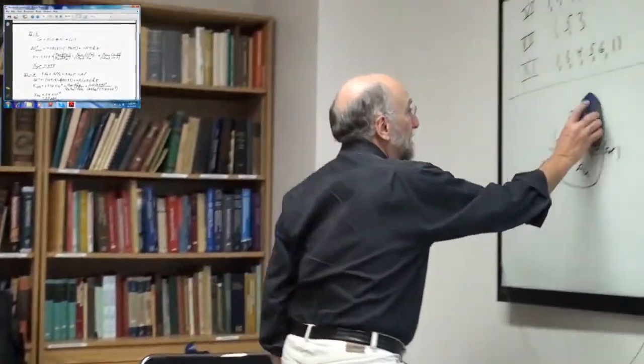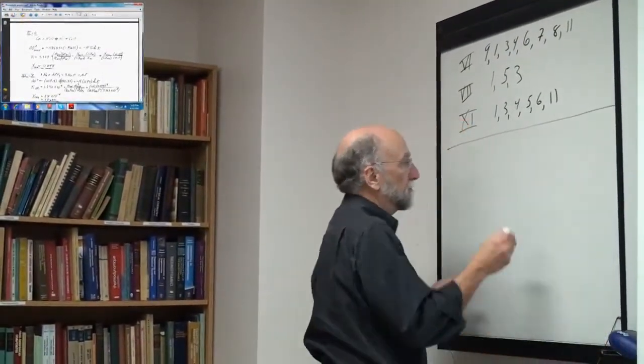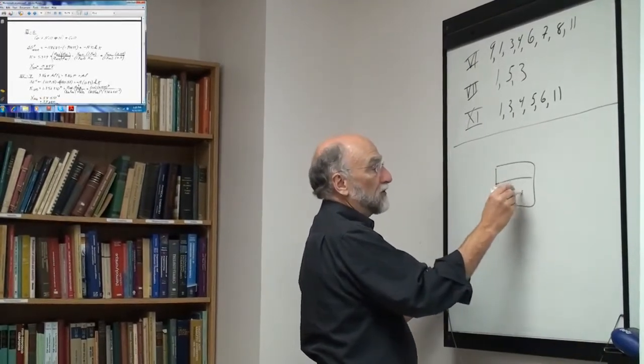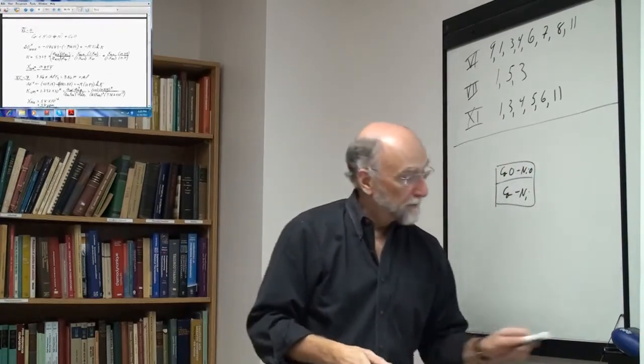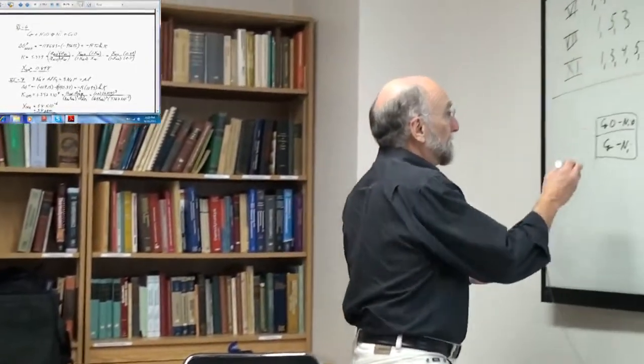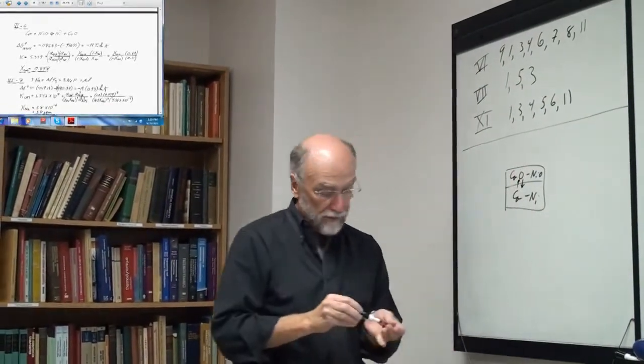Okay, so this is a very classic gas, or you say metal oxide or metal nonmetal or metal slag or whatever, equilibrium. You have an exchange reaction. We have two layers here. Here you have a metal, which is a cobalt nickel solution, and up here you have an oxide, which is a cobalt oxide nickel oxide solution. Okay, and they're in equilibrium at the interface. So we assume that at this interface there's an equilibrium formed between the two phases.